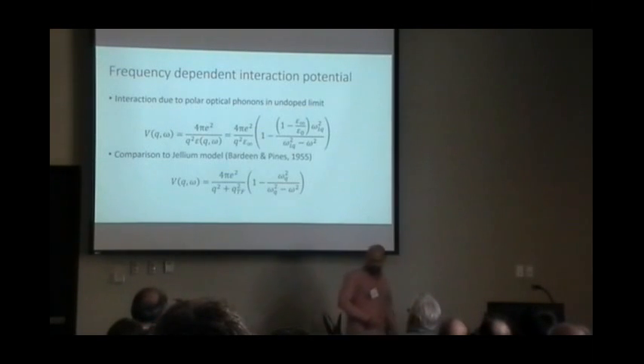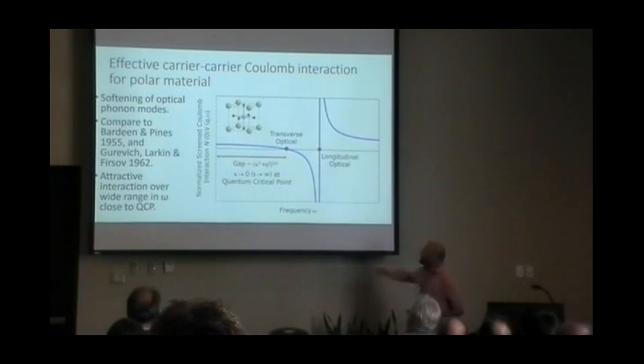So our approach is based on the jellium model of Bardeen and Pines. So if you look at the interaction, normally the Coulomb interaction of two electrons in the undoped material, then you write down the frequency-dependent version, and then you put in the dielectric function dependence on frequency and q, and you can write it out so you get a function for the Coulomb potential that you actually can plot, and where the zeros actually correspond to the transverse optical and the longitudinal optical mode.